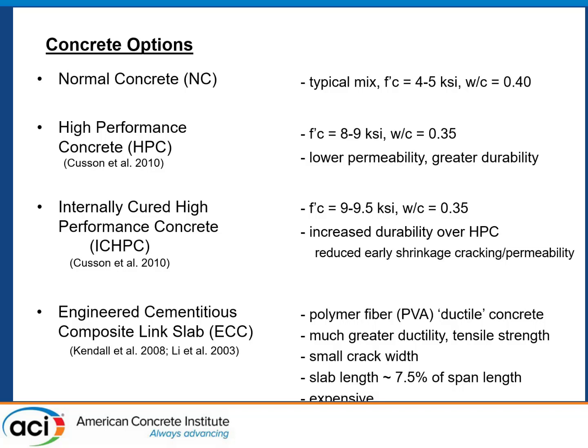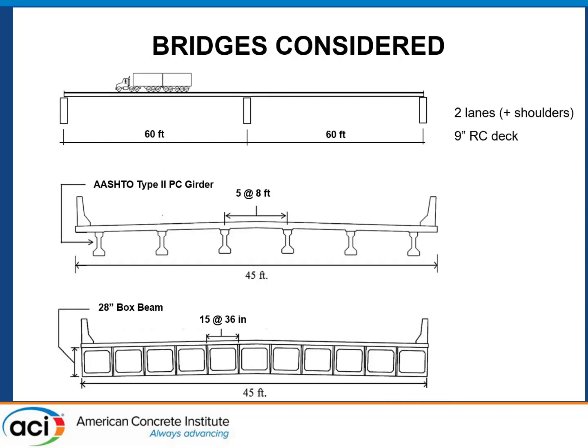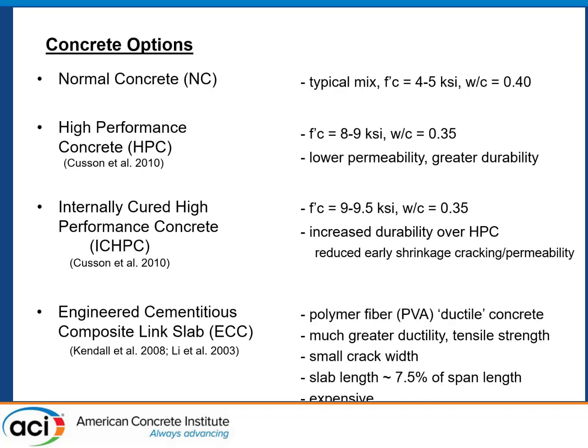The idea here was that rather than have an expansion joint, so in the bridge we often have an expansion joint over the central pier, and of course it deteriorates over time and water leaks down through that crack and then begins to saturate the ends of the girders and causes corrosion of the girder steel. So the idea behind this link slab was to remove that expansion joint and replace about 10 feet or so of the slab itself with very highly ductile, high tensile strength concrete. The drawback is it's very, very expensive.